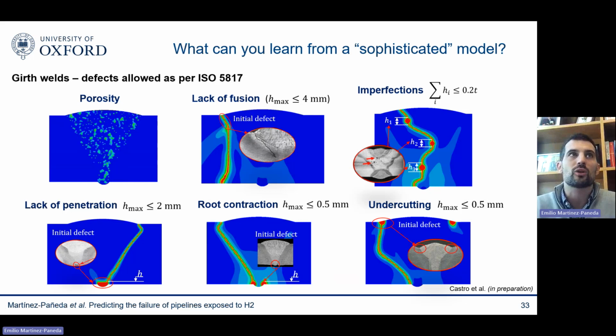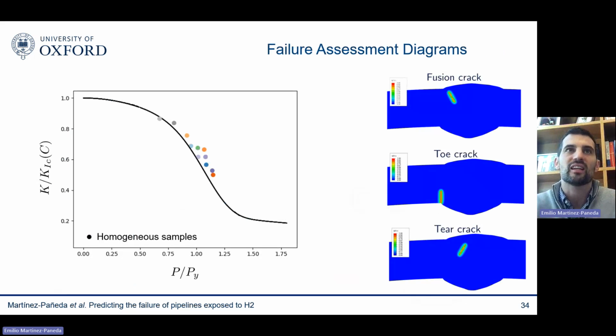The other thing you can do, of course, is consider the conditions of the standard. The standard will tell you under which conditions a weld was considered satisfactory. So a standard will tell you, okay, you are allowed to have a lack of fusion defect below 4 millimeters. You are allowed to have this kind of imperfection. You have lack of penetration defects, root contraction, porosity conditions, undercutting. So you can introduce all of those conditions, and even assuming that the weld has been done perfectly in agreement with the standard, you can quantify the effect of each of those defects when it comes to reducing the critical pressure of your pipeline. So this is some of the things that you can learn from this sophisticated model.